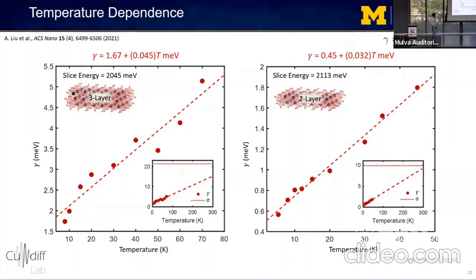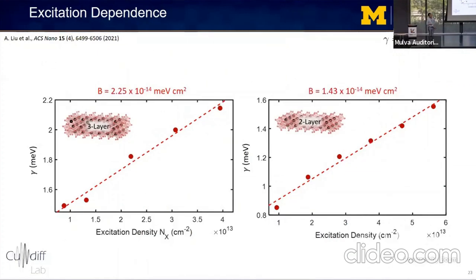So for the 2-layer nanoplatelets, the extrapolated homogeneous line width is comparable to the inhomogeneous line width sigma at room temperature. Whereas for the 3-layer nanoplatelets, there's still a significant difference at room temperature. So this means that the common assumption of homogeneously broadened exciton resonances at room temperature should be applied with care in thicker colloidal nanoplatelets.